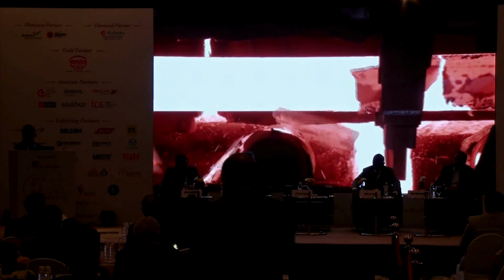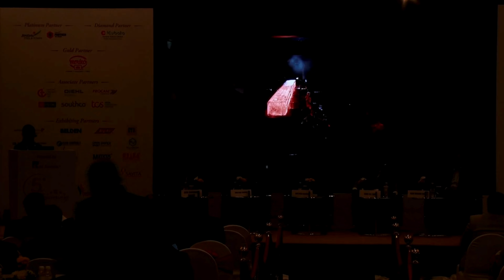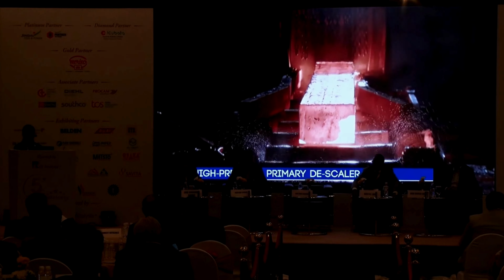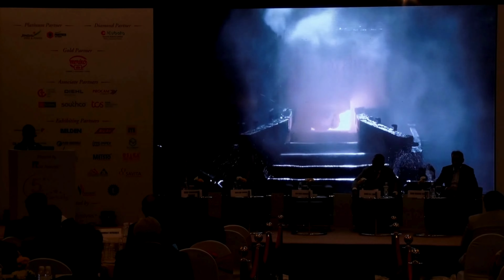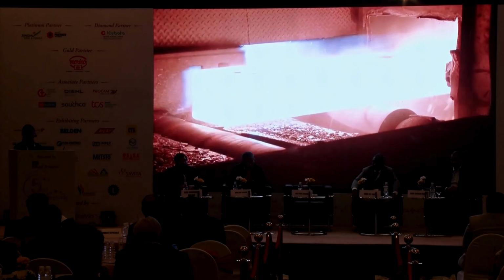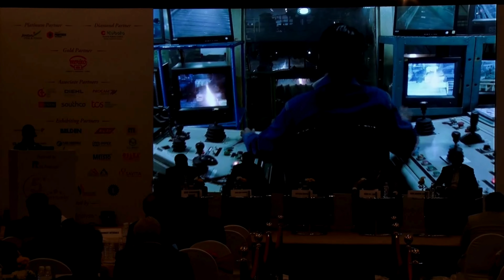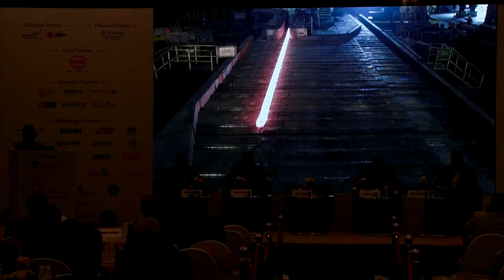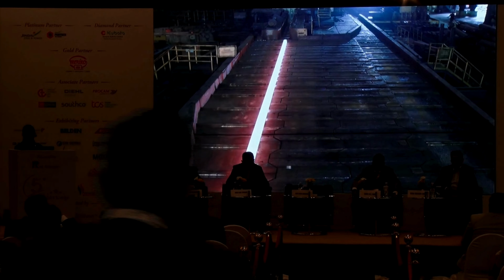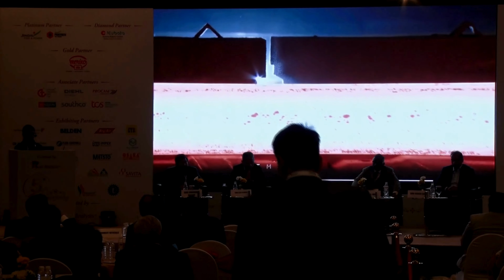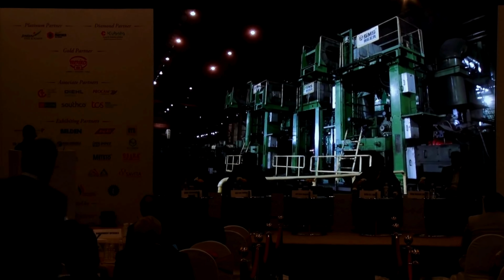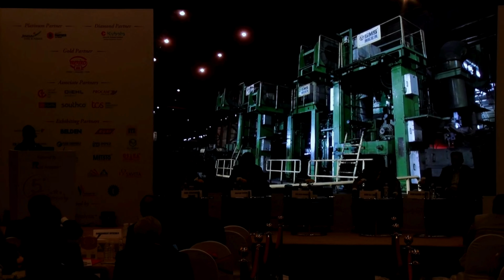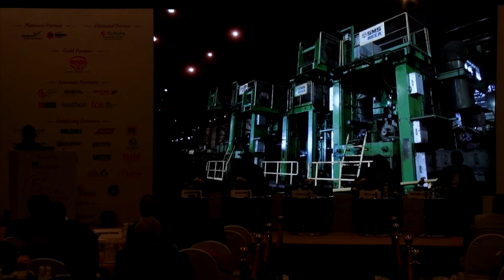The uniformly heated blooms are immediately passed through the high-pressure primary descaler to achieve scale-free surface. Water jet at a high pressure of 200 bar ensures a clean surface. Rail rolling is done using universal rolling. The heated blooms are rolled in the mill through breakdown stand, intermediate stand, and then the tandem mill, which consists of universal roughing, universal edger, and universal finishing stands.